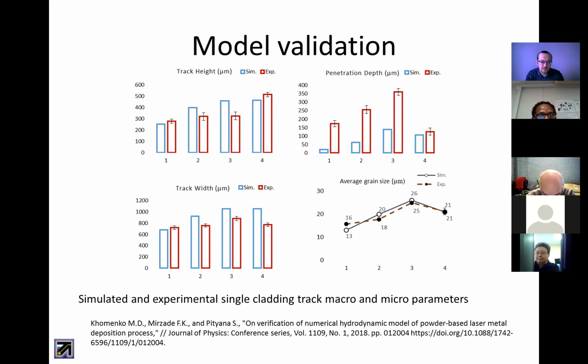After that, we validated the results of the model. It showed rather good comparison with the experimental data for the micro parameters of the track and for the macro parameters of the track, excluding the penetration depth, which could not be well resolved in our model, but we are not aiming to investigate penetration depth in our future calculation. That's why it's not a great problem.